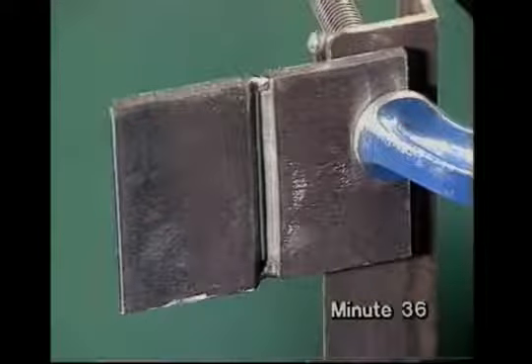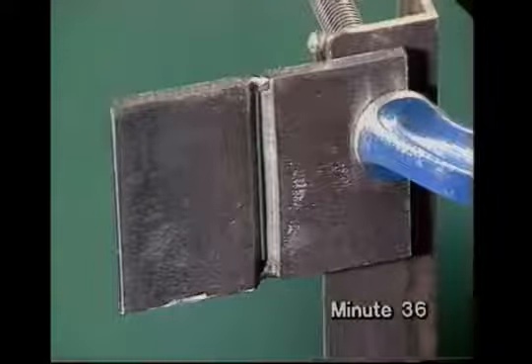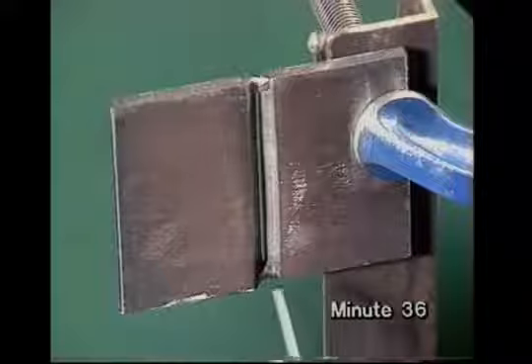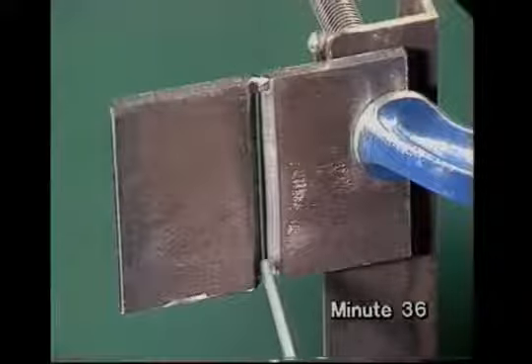A similar butt joint in thick metal to the one welded flat is prepared in the same way and welded upwards. If Max sees the edges start to burn through, he slows down, weaves and flicks the electrode to regain control of the molten metal.